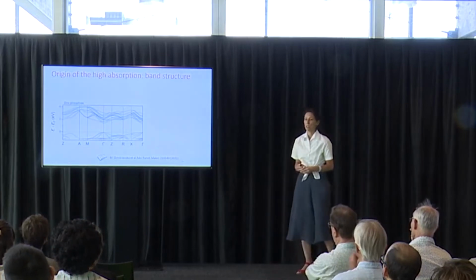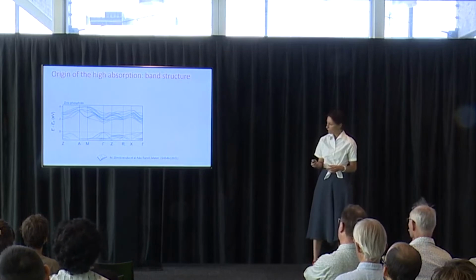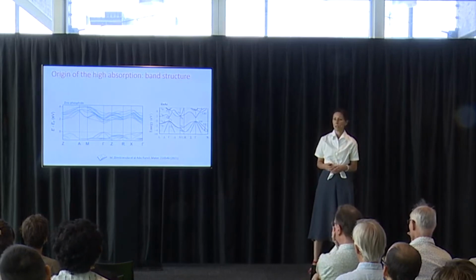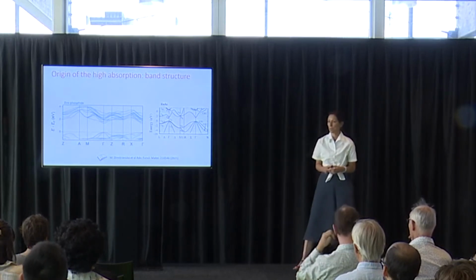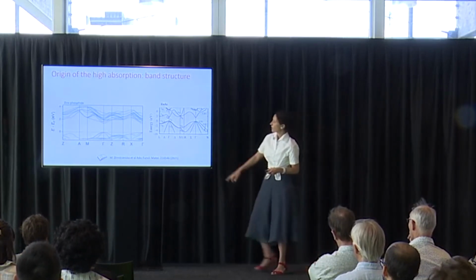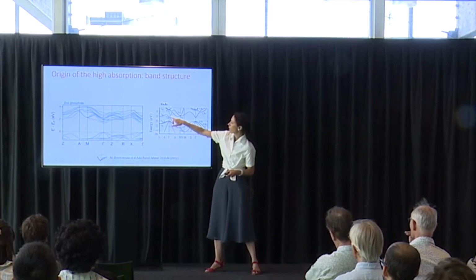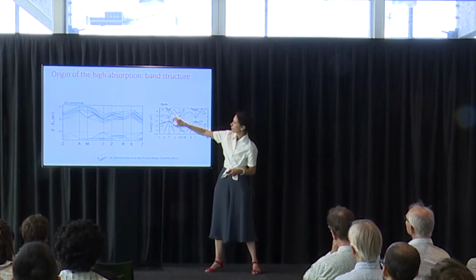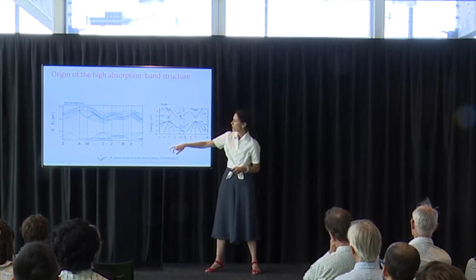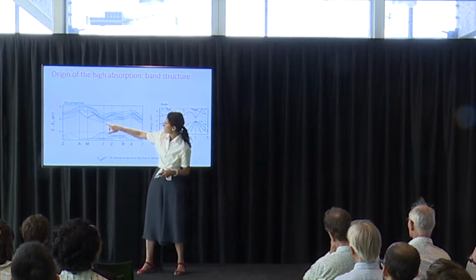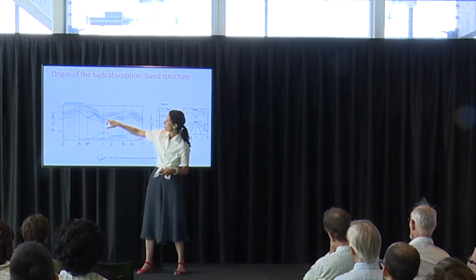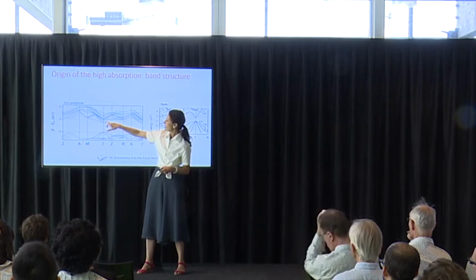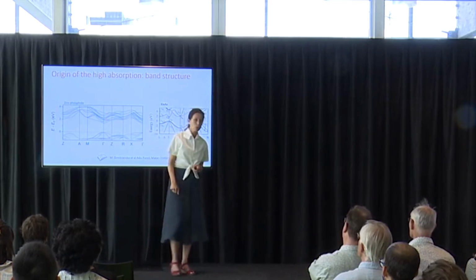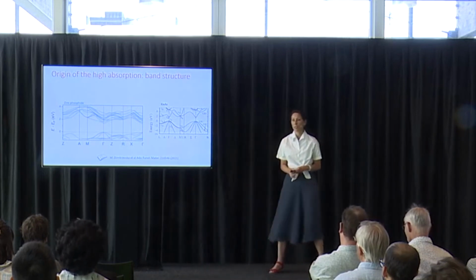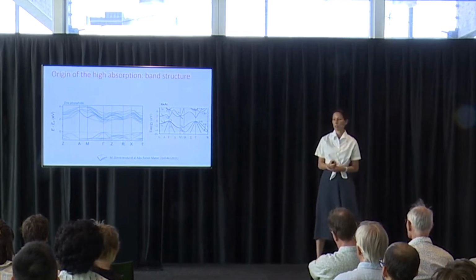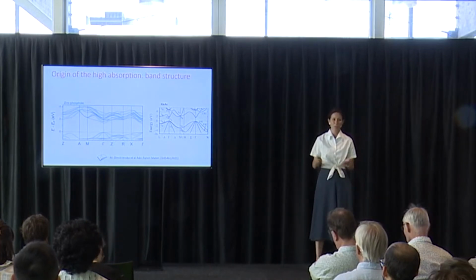One of the reasons for that is the band structure. Here I compare the band structure of gallium arsenide and zinc phosphide, and the band structure on the left was simulated by one of our collaborators. What you see in gallium arsenide is the band gap here, and you see that there is one conduction band and the next one is quite far away. I put them in a similar scale so that you see it. And with the zinc phosphide, after the band gap, you have many conduction bands here. And these are all the transitions that we saw in the electron loss spectroscopy. These are all transitions that are happening from the valence band. And this is what makes a very high absorption coefficient in this material. So here, we were just lucky. Nature has been nice to us when we chose the material. It has to happen sometimes.